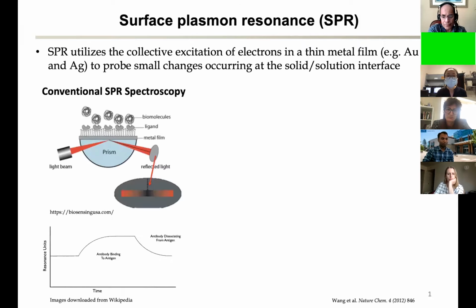You might be familiar with the traditional SPR technique. In conventional SPR spectroscopy, the SPR utilizes the collective excitation of electrons in a thin gold film. It can be used to probe small changes occurring at the solid-solution interface, so typically it's used to study interactions between biomolecules. For example, in the traditional setup, the detector measures the drift in the SPR resonance angle. As a result, you can get a sensorgram, which can monitor a molecular interaction, for example, antibody-antigen interaction. But in a word, you're getting a spectrum type of signal.